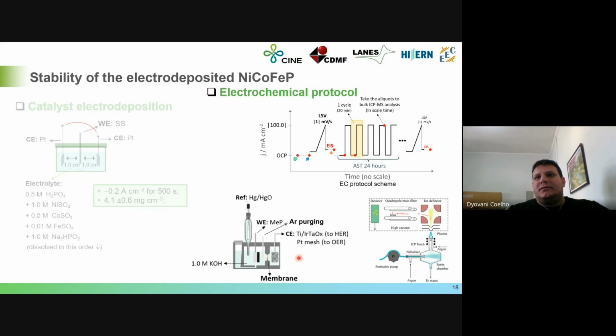And an aliquot of the solution was taken time by time, which are these red dots here, just to see what is the electrolyte composition and what is happening with my catalyst, tracking the metals in my catalyst, like nickel, iron, and cobalt. The phosphorus I couldn't track. It was really hard. I tried, but I couldn't. But it should be interesting to track too, the phosphorus content in the electrolyte. And this tracking was made by ICP-MS.